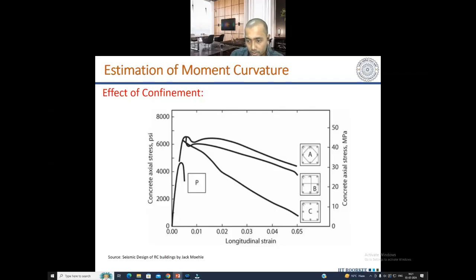These curves have a strain limit up to 0.05, but this plain concrete has less than 0.01, or maybe 0.005. So it is almost one tenth. Compared to the unconfined concrete, your confined concrete can have a strain limit up to 10 times that of normal concrete. In terms of strength, the difference is not very much, but still it is higher. Here you have around 4000, 4200 or so PSI, and in case of confined, it is around 6000.